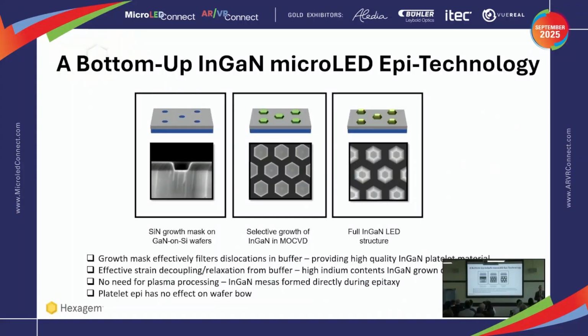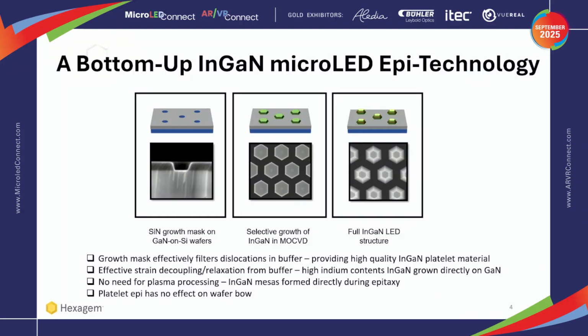So our approach is a bottom-up technology. It's non-planar. We are still using gallium nitride buffers on silicon or sapphire. The quality doesn't need to be great. It can be thin layers, high dislocation density. It's all fine. We put a growth mask on, typically silicon nitride, and then we pattern small openings in this growth mask down to the gallium nitride buffer. And then using conventional 3-nitride MOCVD, we grow indium gallium nitride selectively in these openings. So we create, as you see in the middle here, these InGaN platelets.